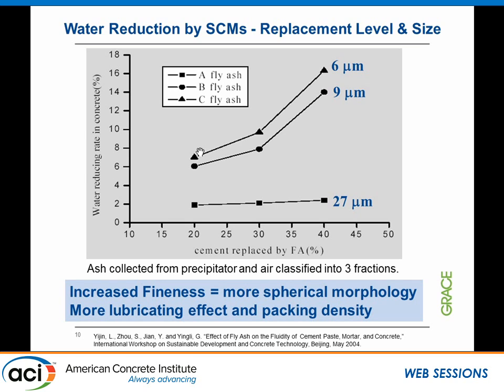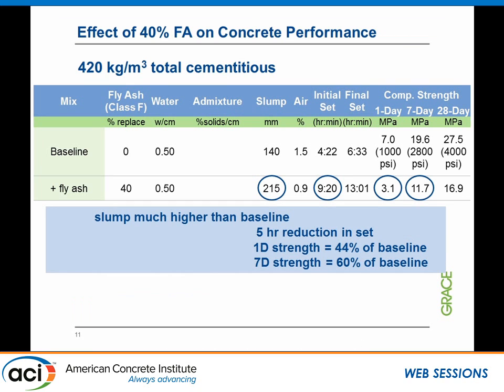But when she was using the finer fly ash, definitely she saw a much higher water reduction level. The reason for that is because in this case, the finer fly ash has more spherical morphology. So therefore, you're getting a lubrication effect, and more importantly, a packing density effect, and therefore strength increase.